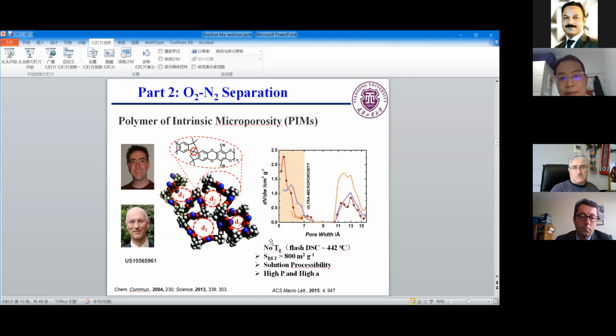Although recently, some people reported that using flash DSC, they can get a glass transition temperature of about 440, which is very, very close to the decomposition temperature of this membrane, because they decompose at 450. These polymers have a very high BET surface area, around 800 square meters per gram. The most important thing we need to emphasize is that these polymers are solution processable. Now we can process these membranes like conventional polymers using the solution method, and they also demonstrate very high